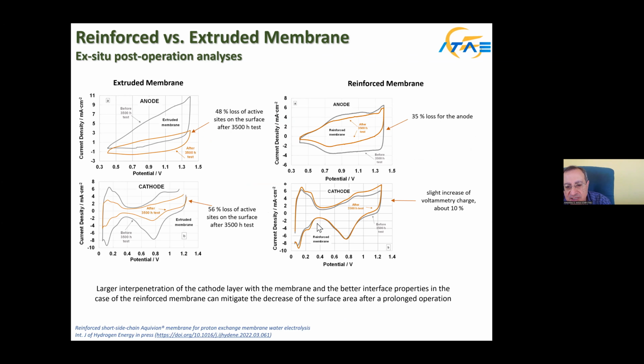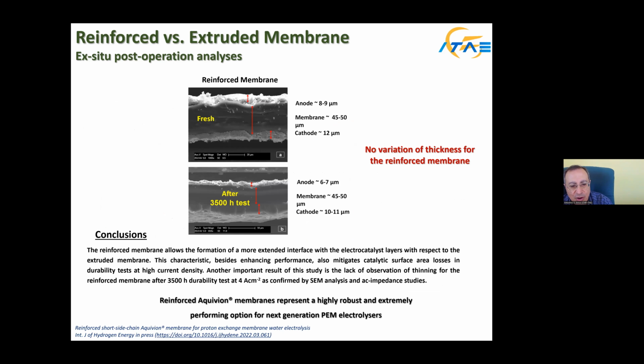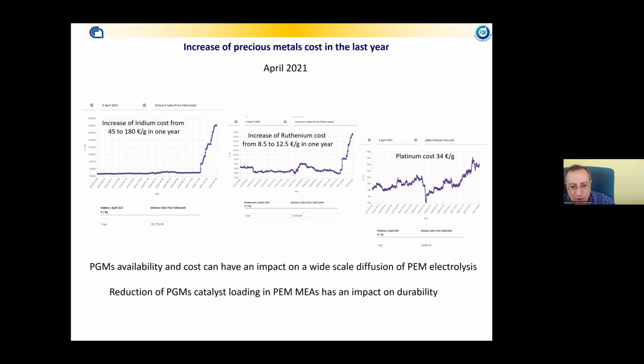As you can see from these cyclic voltammetry studies, we have nice cyclic voltammetry from the cathode and also from the anode. The cathode is not changing much after 3,500 hours of operation. Some changes are observed at the anode, you can see a decrease of the capacitance. This is another important in situ diagnostic tool to understand variations, and ex situ SEM, EDX, and XPS are also really important.